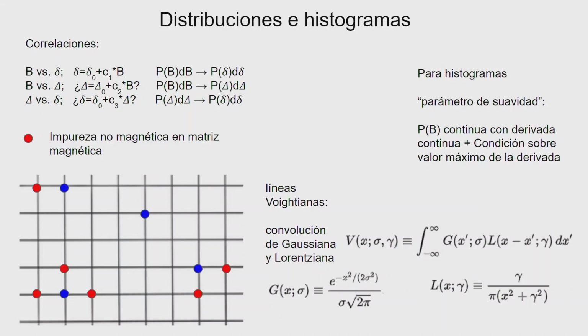So to take this asymmetry, because you have isomer shift and also the magnetic hyperfine splitting, it must always be based on a physical model. If you change one atom of the material next to the probe with a different one, with a different electronic density, then you would expect a change in the isomer shift. And if it also affects the magnetic properties and the magnetic hyperfine field, you may assume that there is a correlation between the two parameters, and the simplest assumption is that this correlation is linear. But this is a sequence of assumptions which must be very well physically supported.